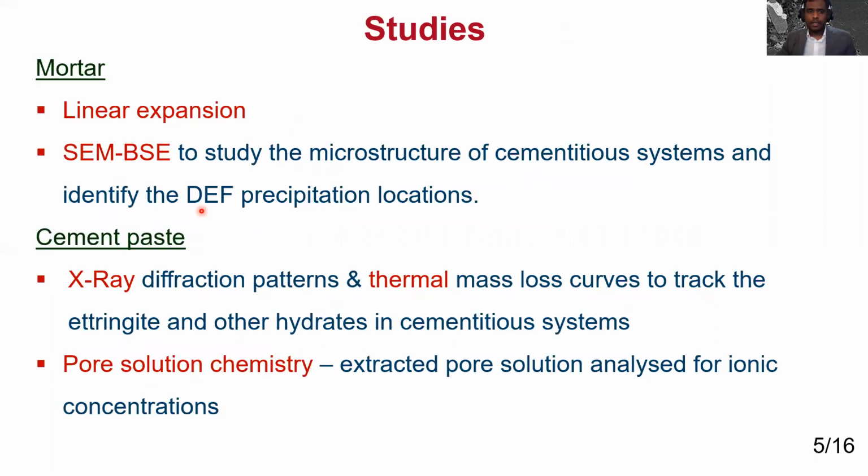So we have done some basic DEF tests like linear expansion studies and a microstructure analysis with the help of SEM to understand where the DEF precipitation occurs, track the location, and other characterization studies such as X-ray diffraction and thermal mass loss curves to track the ettringite formation in the cementitious system. And finally, pore solution chemistry by extracting the pore solution of hardened cement paste and studying it over a period of time, say starting from 4 hours to 30 days.